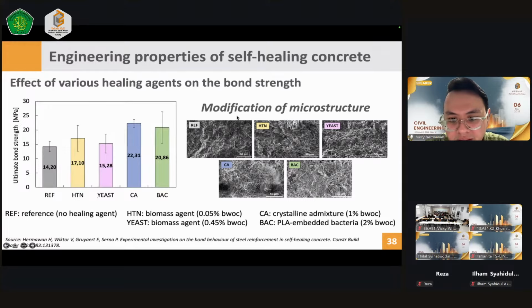So here I also show some pictures of the modification of the microstructure of the concrete. If you compare with the reference HTN and the yeast, the contour or the matrix of the concrete is very amorphous. I mean, we cannot distinguish the size, but they are covered mainly by the tobermorite gel or the calcium silicate hydrate gel. But with the crystal admixture and the bacteria, they are very distinct if we compare with the reference and the other matrix. Because of what?